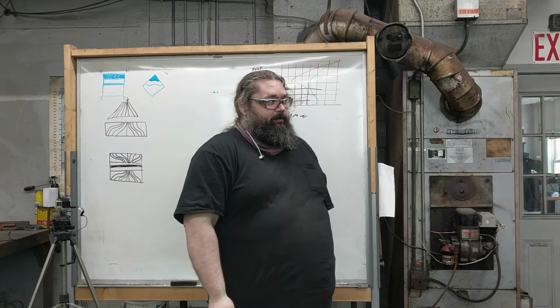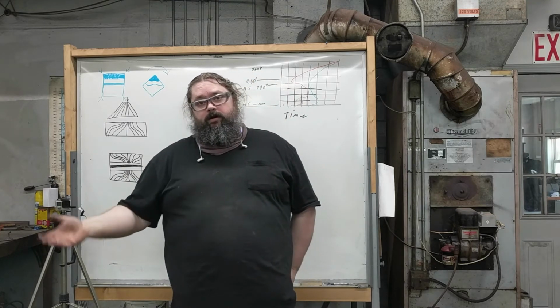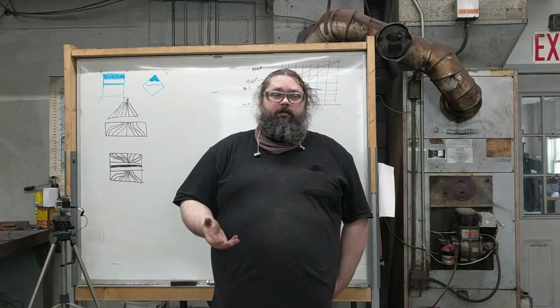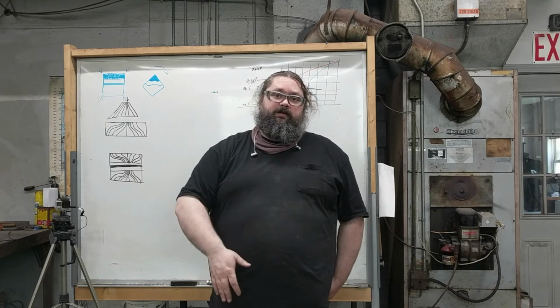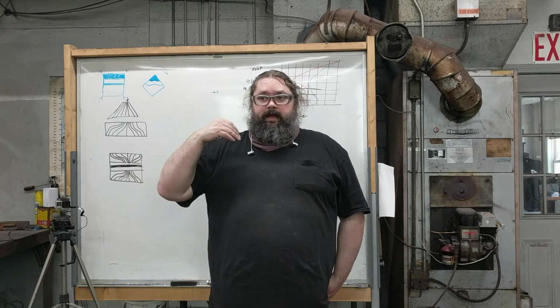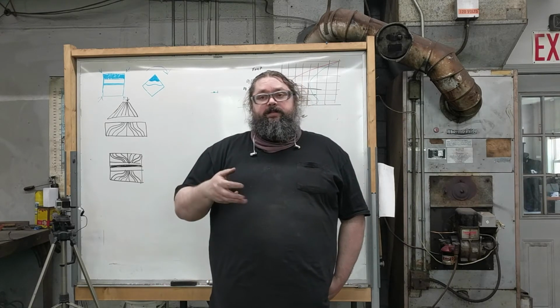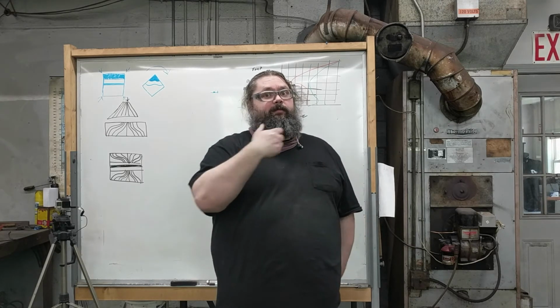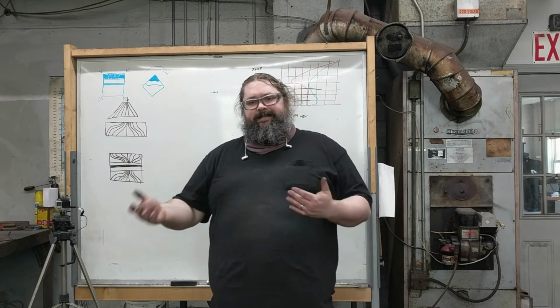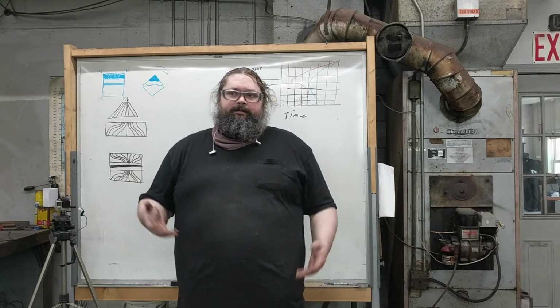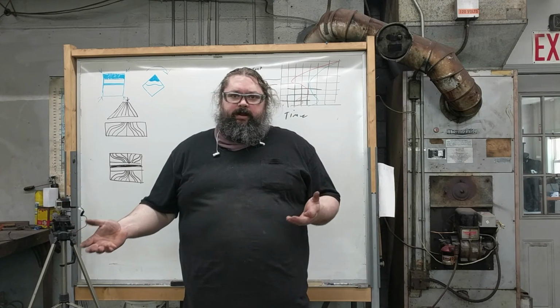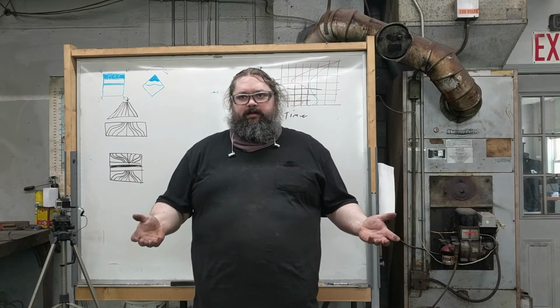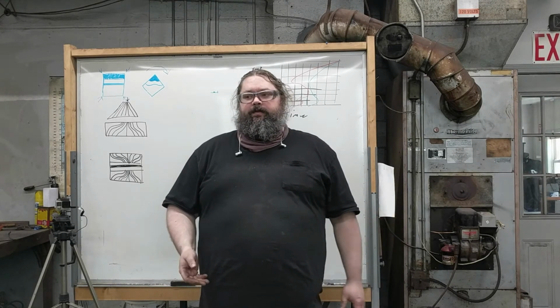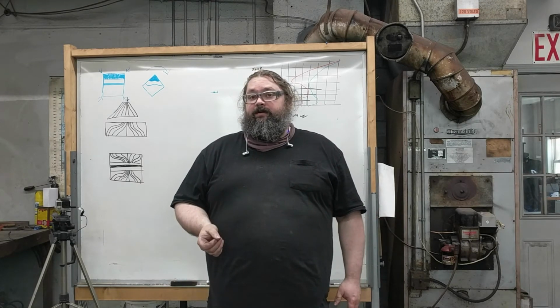So then we want to temper at the temperature we're going for hardness. In this case, I'm going to go about 400 degrees, which should give me about 60 Rockwell, 61. And I'll do that 3 times. The reason I do that 3 times is every time I'm tempering, I'm getting a little bit more retained austenite converted. It's just a safe bet to do 3. After 3, anything that's not converted isn't going to be converted. It's probably stable at that point. It's probably nickel based. So that is the reason we need to cryo on stainlesses.